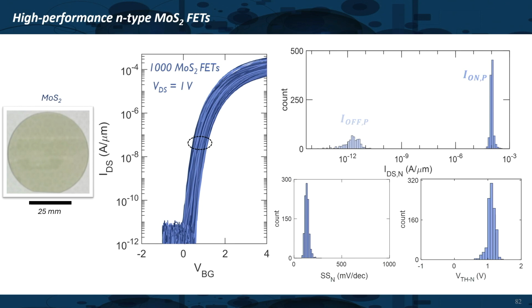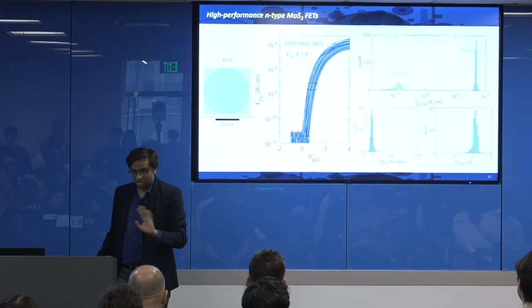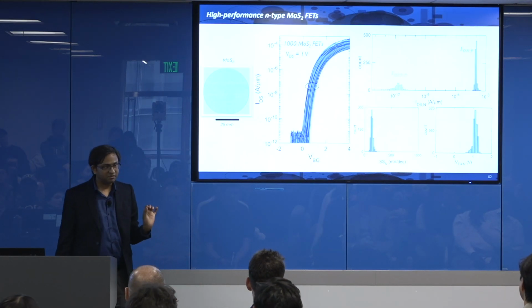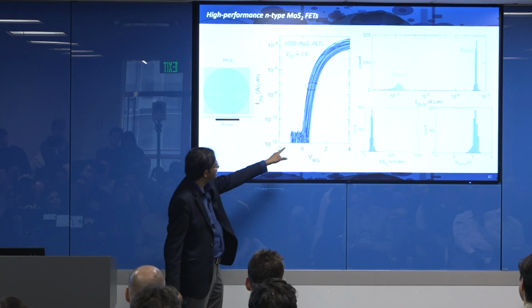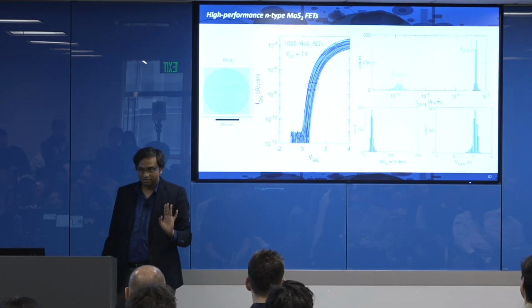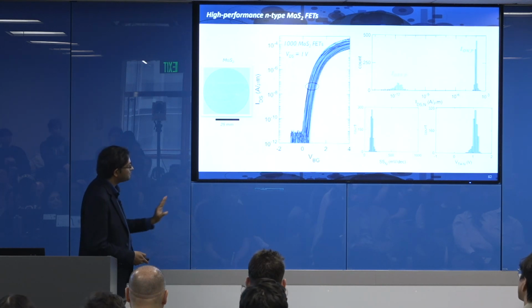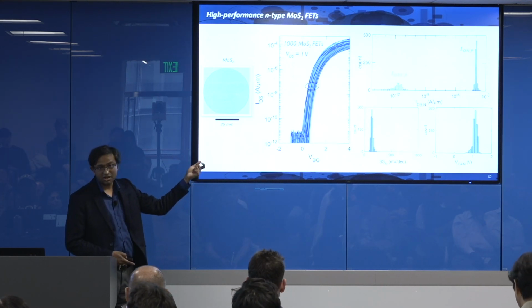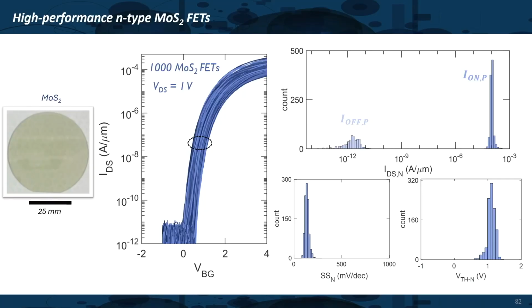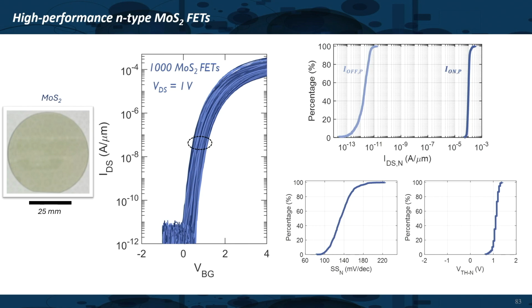So with a large number of devices, we have been able to get to very high on-state current, and we have been able to reduce the off current at Vg equal to 0. The on/off ratio always existed with the 2D material, but what we could not do is bring down the off current to low values at Vg equal to 0. So we were able to do that with some growth optimization, and you can see that the device-to-device variation has also gone down quite a bit. And then you can do all this statistical plot, and you can see that the threshold voltage variation is actually quite low. And if you compare it with the existing silicon technology, it is getting there. It's still not there. I will show you some more slides on that.